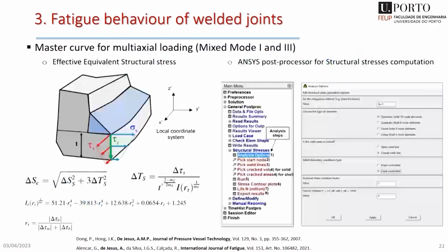Recently, with a new student, a PhD student in civil engineering, we implemented this idea of the master curve structural stress in an ANSYS post-processing model. Besides the mode 1 fatigue cracking, we added the mixed mode, mode 1 and mode 3, leading to the effective equivalent structural stress. So nowadays, this is open for use. You can download the paper, you can install the routines if you have ANSYS, and you can run this for your welded joints. And it accounts for mode 1 and mode 3, so a multi-axial process.